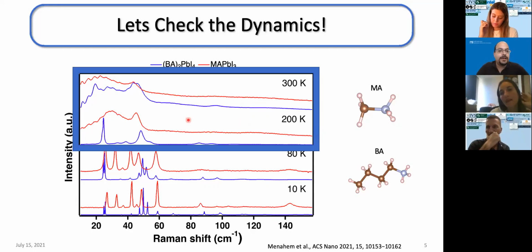So at 200 Kelvin, methyl ammonium lead iodide has already undergone a phase transition to a tetragonal phase, and we see that the Raman spectrum is very broad and features are indistinguishable. And at 300 Kelvin, butyl ammonium lead iodide also underwent a phase transition with a similar effect on the Raman spectrum, where everything is broadened and features are highly indistinguishable, but its symmetry didn't change. It remained orthorhombic even in the high temperature phase.